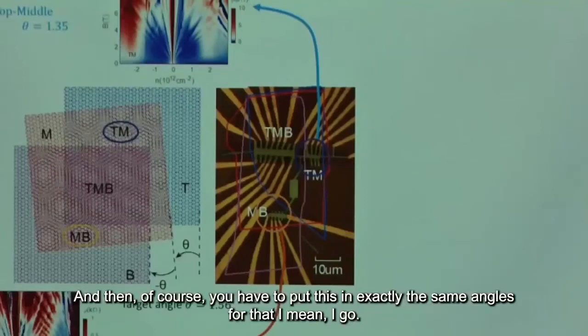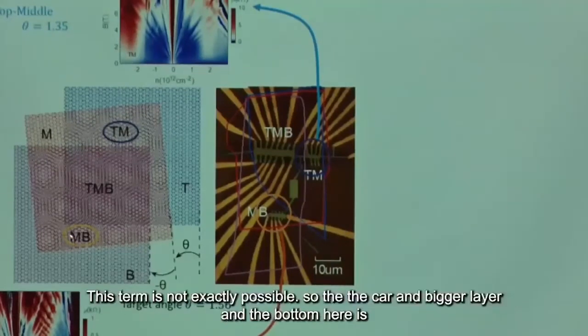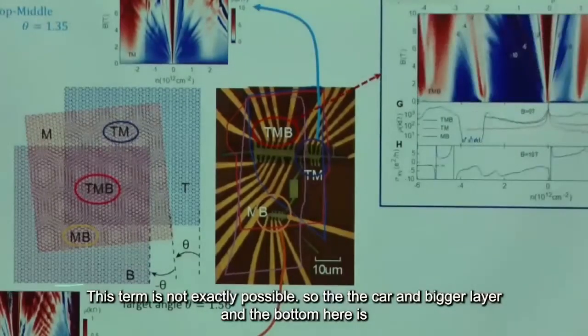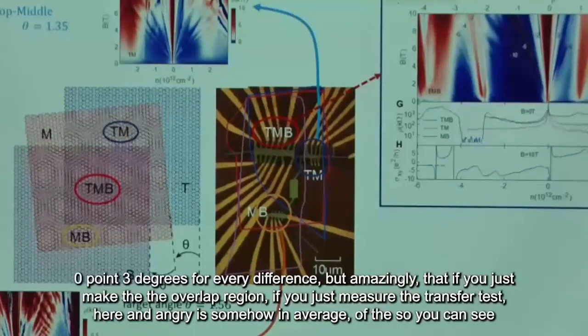Experimentally, it's not exactly possible. So between the top and middle layer and the middle and bottom layer, there is an angle difference between 1.35 and 1.66, about 0.3 degrees. But amazingly, if you just measure the transport in the overlap region, it is clear, and the angle is somehow the average of the two layers.